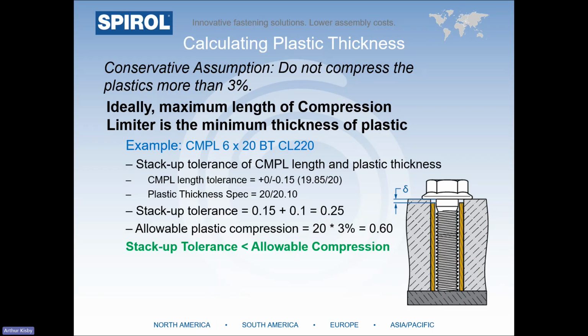Remember, there are two rules for compression limiter length as it relates to the plastic thickness. One, the compression limiter must bottom out against the mating component or the bolt head or washer once the bolt is tightened. And two, ideally the plastic will have a slight amount of compression when the bolt is tightened. To achieve both of these design criteria, the maximum compression limiter length should be equal to the minimum plastic thickness.